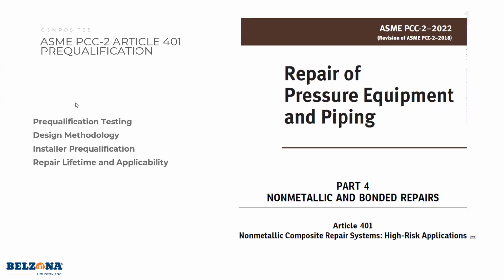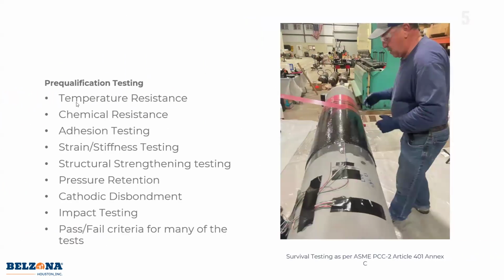So I'm going to kick it off with some of the pre-qualification testing. So what we have here is a composite material. Ours, specifically Belzona SuperWrap II, is a carbon fiber fiberglass reinforcement sheet that is saturated with an epoxy resin. And the epoxy resin is liquid. When you mix it, it saturates the cloth, and then once it cures, it forms a hard composite, similar to a cast. So the epoxy resin has certain limitations, just like the fiber itself, the carbon fiber has limitations.